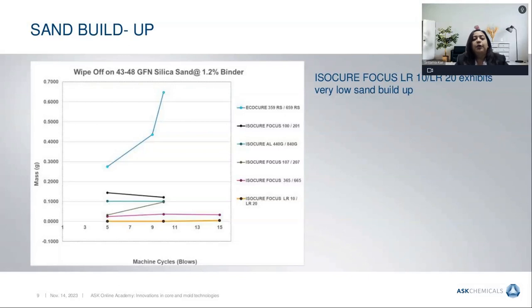Now I'm going to show you some experimental data of this product. So this graph represents a comparison of sand buildup between our different products. The y-axis represents the amount of sand buildup, and the x-axis represents the number of blows per sample. And this test was done with the new tooling that we developed for resin wipe-off. So the lower the y-axis value is, the better the performance of the product for sand buildup.